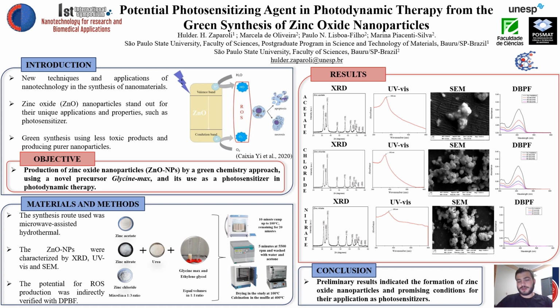Finally, the powder was dried in the oven at 100 degrees Celsius for 12 hours, and in a muffle furnace for 2 hours. For the characterization of the nanoparticles, X-ray diffraction, scanning electron microscopy, and UV spectroscopy were used. And for the production of ROS, the potential was evaluated indirectly using a solution of nanomaterials with DPBF probe.